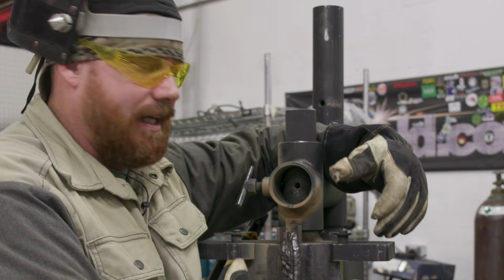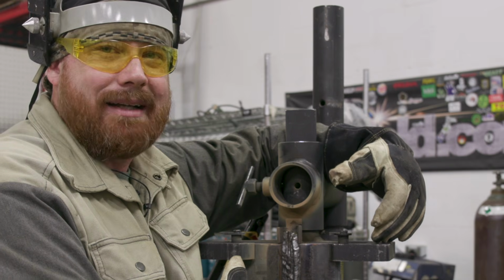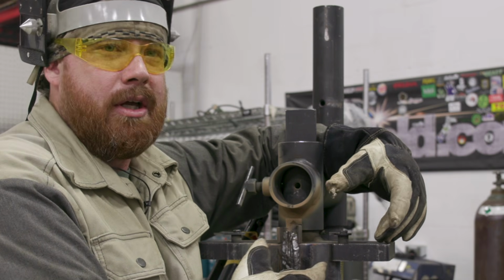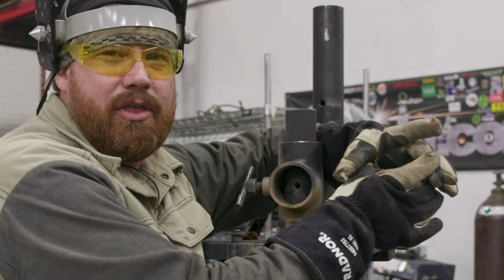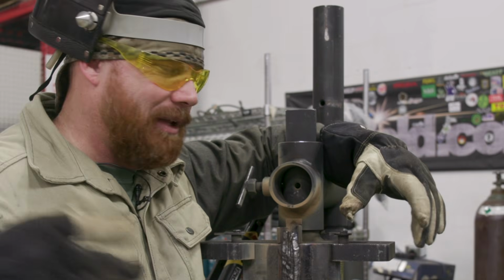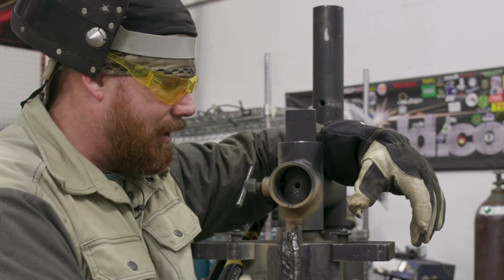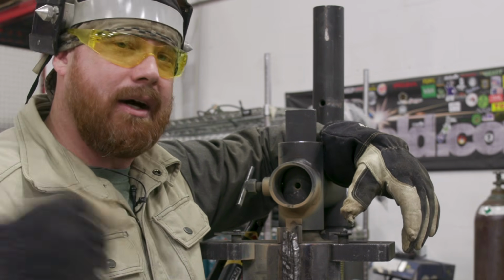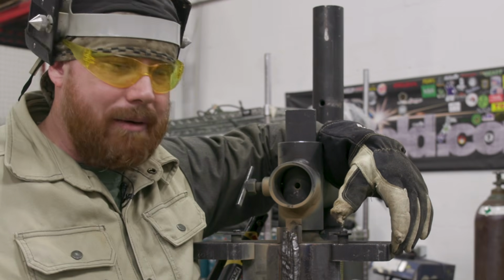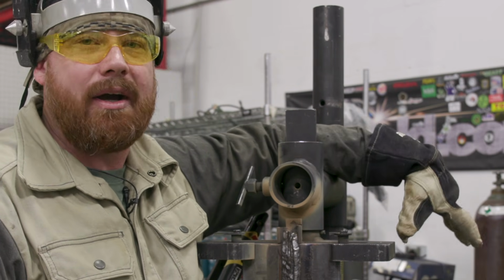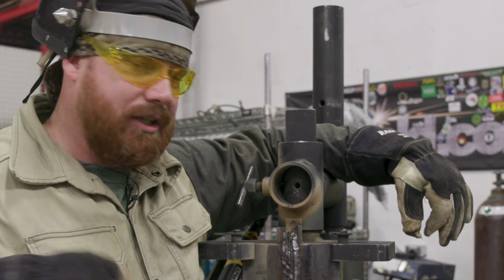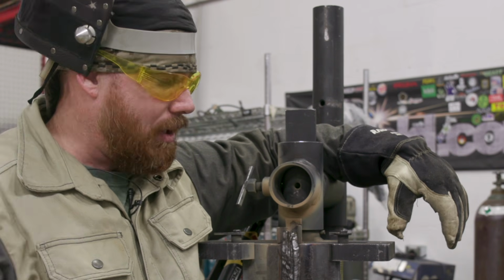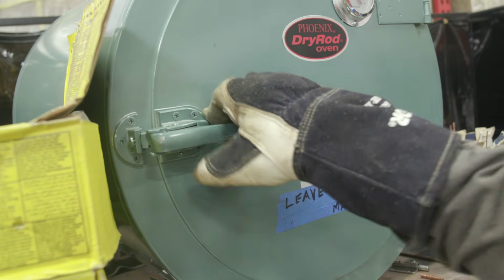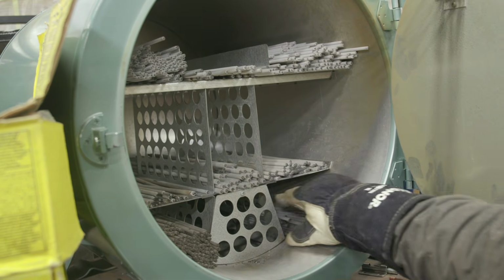Because this test plate is going to take a significantly long amount of time, you don't want to go grab all your 20, 30 rods at one time. I only grab like 4 or 5 rods at a time. I'll put a layer in, and then for the next layer I'll go grab another small handful of rods. I don't want to leave them out here soaking up hydrogen. So I just get what I need as I need it. They're gonna burn a lot better when you pull them right out of the rod oven versus if they've been sitting out on the desk or the bench for a while.